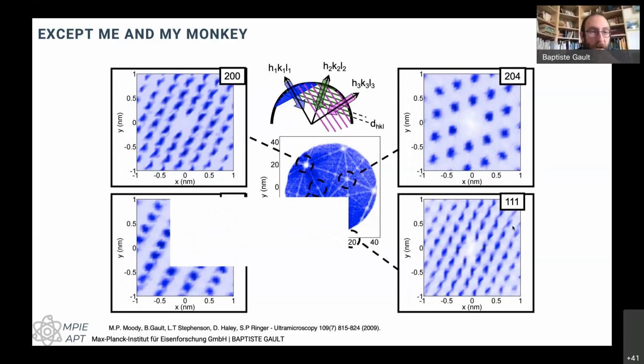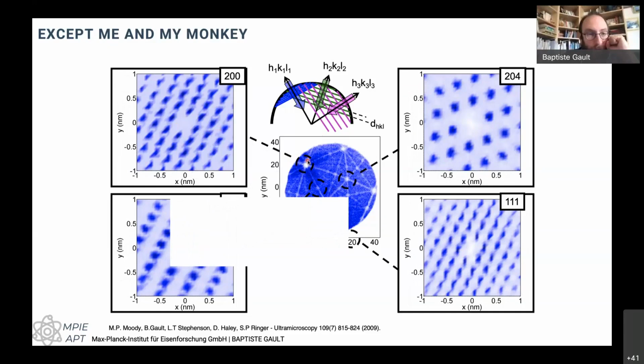So I can also look within one of these planes, what is the average distance between the atoms? And in that case, I can see a pattern forming. So I'll get back to my laser pointer. I can see a pattern forming that actually corresponds to what I would expect on a 111 plane. As you can see, the 6 atoms sitting there, so the really dense, closely packed planes.